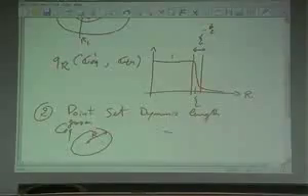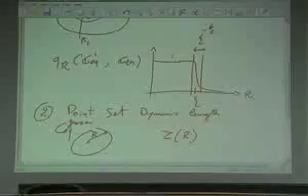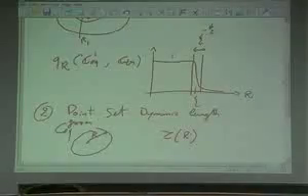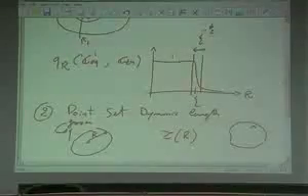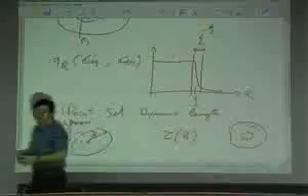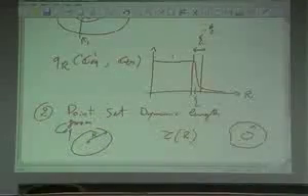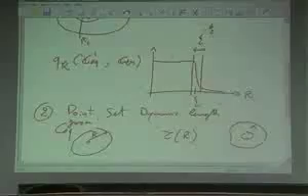And now I'm computing how the time scale goes as a function of r. Now, what should I expect if the mosaic is right? Well, if r is less than xi, I have the boundary condition that fixes me inside one state. So let's do it again. I have alpha here, and inside my cavity, the boundary condition fixes me in the same state alpha. So the relaxation time will be very fast, because the system doesn't really have to relax. It's just frozen inside alpha. So tau of r will, in principle, be small.